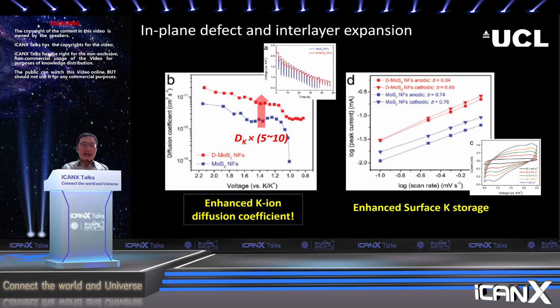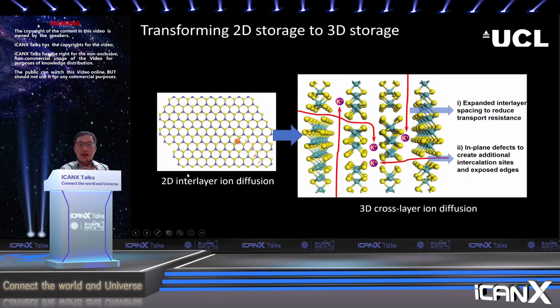So as I explained in the beginning of this work, in an original 2D molybdenum sulfide where there are no defects in each layer, the diffusion of the ions is on the surface of each layer and in between the two layers. So it forms a 2D interlayer ion diffusion manner. But by introducing the defects into each layer, we open up the pathways for ions to go into the material, and we open up the interlayer space where ions have higher freedom to move around inside the interlayer space. So we essentially change the 2D interlayer ion diffusion into a 3D cross-layer ion diffusion.